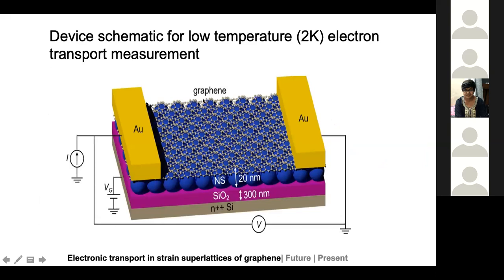Okay, so let's now talk about the electronic transport in such a system. This is a schematic of the device which was used for transport measurements, two-point measurements. You have these gold leads deposited on either side. You pass a current through it and record the resistivity. All the measurements were done at 2 kelvins, and there is a gate voltage applied using this silicon electrode at the bottom, and that gives you control over the number of charge carriers in the system.